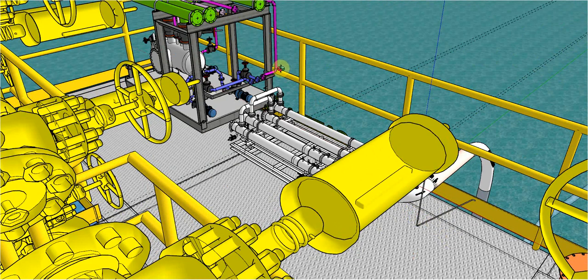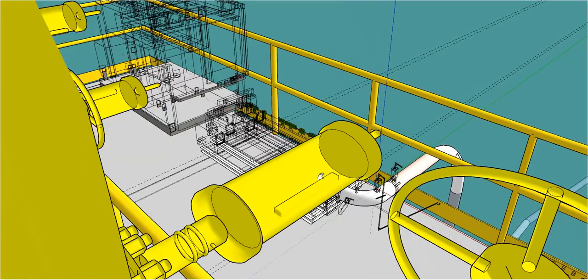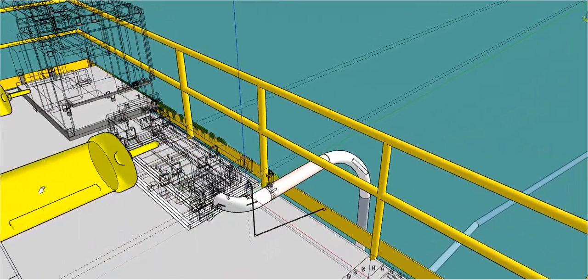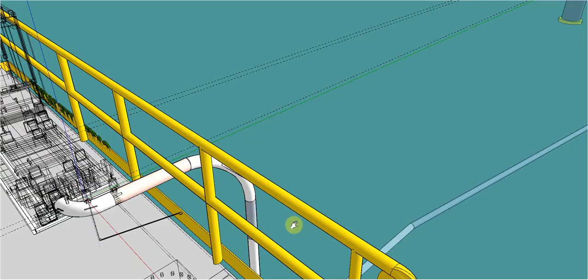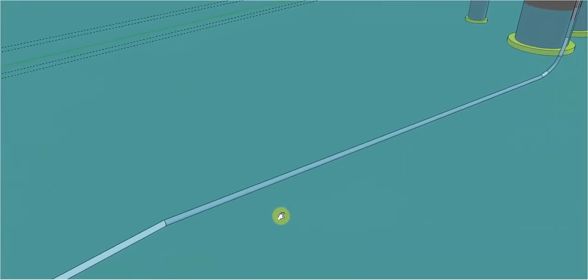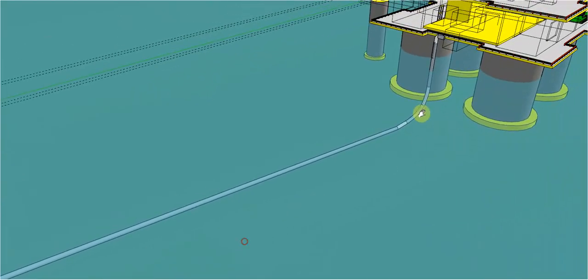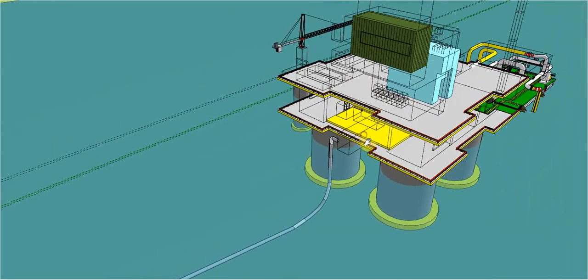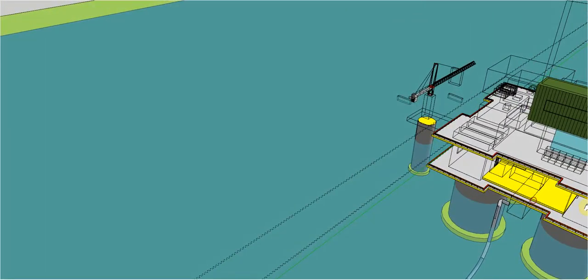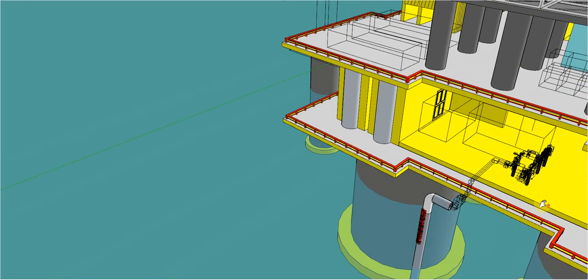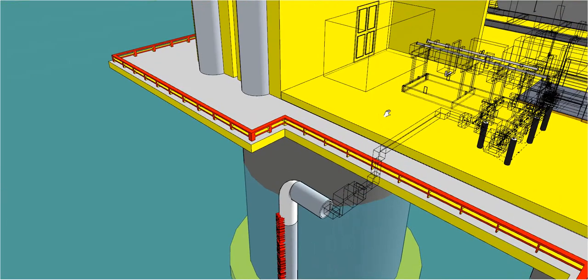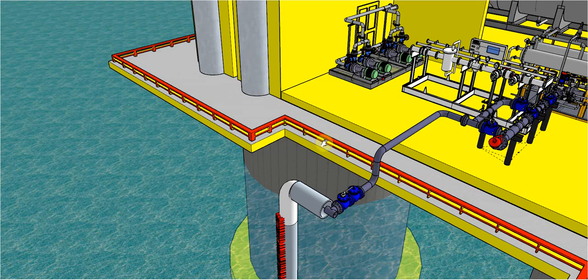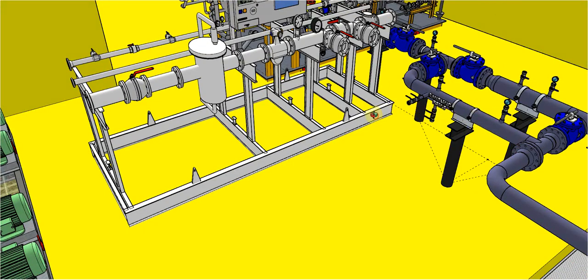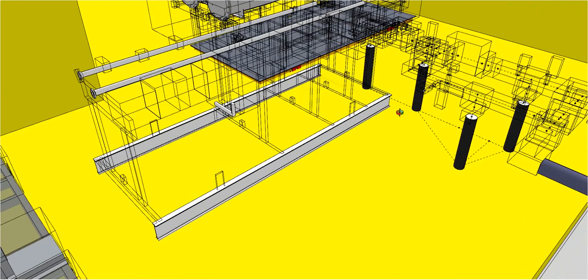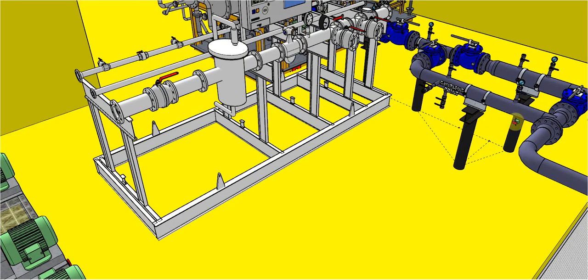Since interference in organic acid corrosivity measurement can be affected by MIC, or microbial induced corrosion, we need to perform SRB and APB analysis as per API RP 38 MIC mapping, which includes enumeration and inoculation for at least 14 days. Several samples require analysis onshore using sophisticated equipment.